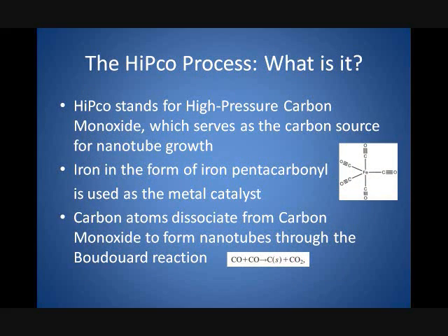So what is the HiPco process? HiPco stands for high-pressure carbon monoxide, which serves as the carbon source for nanotube growth. Iron in the form of iron pentacarbonyl is used as the metal catalyst. Carbon atoms dissociate from carbon monoxide to form nanotubes through the Boudouard reaction.